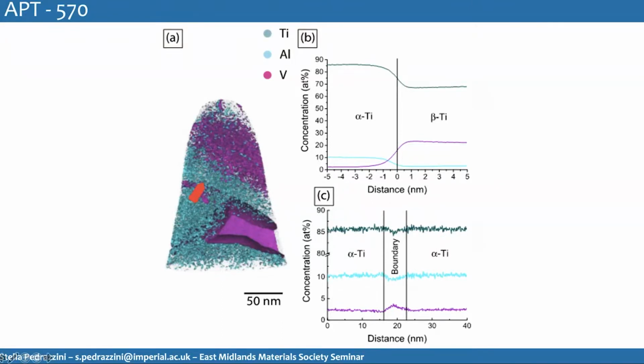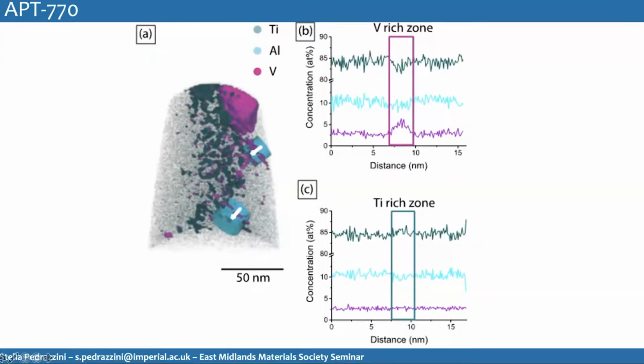And at 770, there's still some evidence of this. So the dislocations are still enriched in vanadium, but they don't look mobile anymore, and the sample is failing in an extremely brittle manner. After this study, I had a student who did thermodynamic predictions and calculations about whether or not there was sufficient vanadium going to the dislocations to nucleate beta there. Through thermodynamic predictions, she was able to show that no, not really. And we also didn't detect any specific oxygen increase at dislocations, which is quite interesting.